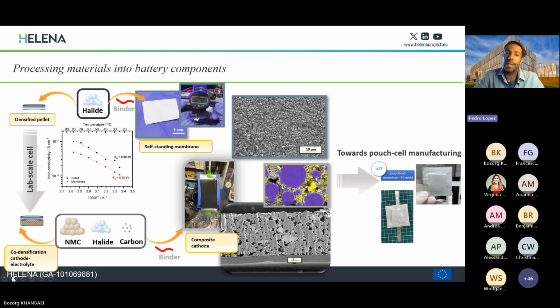And now we are on the step of integrating both the separator, the composite cathode, and the lithium metal into these 40 milliampere hour monolayer pouch cells to then scale up to multi-layer pouch cells of 1 to 5 ampere hour. Please, next slide.